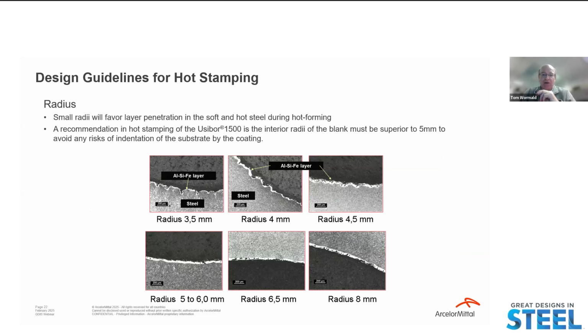One of the potential drawbacks of using too small radii in the hot stamping operation is illustrated here. It's possible for the coating to actually penetrate the relatively soft steel substrate at these high temperatures, creating indentations as shown in this picture. This phenomenon is avoided by following the recommended guidelines we just spoke about for minimum radii. In these pictures, you see how the coating has actually penetrated into the steel substrate, creating this sawtooth pattern that you see in all the pictures labeled from 3.5 to 4.5 millimeter radius. At 5 millimeter and greater, that sawtooth pattern has been completely avoided, backing up that 5 millimeter rule of thumb as being very important for part design.